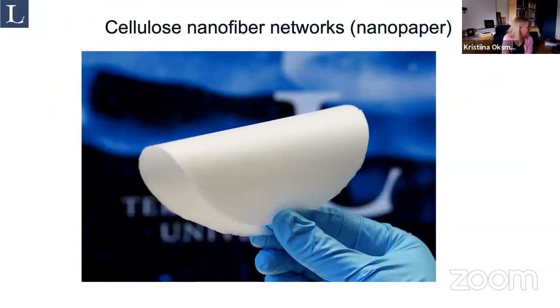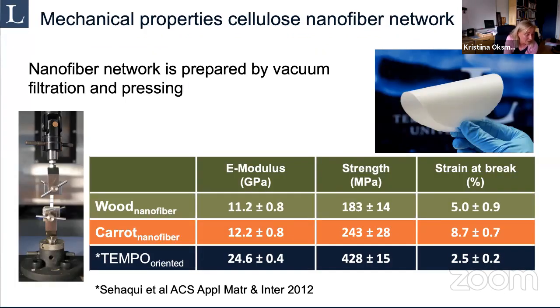Then I have the last example here about cellulose nanofiber networks. I told you earlier that nanocellulose forms this strong network, which we can also call nanopaper. And the properties of these networks are quite impressive. So if we take a look at, for example, carrot nanofiber network, we have a modulus of 12, almost 13 maybe, and strength about 250. It's a little bit better than wood-based nanofiber networks. And the reason for that is that these carrot nanofibers have a more homogeneous fiber size.